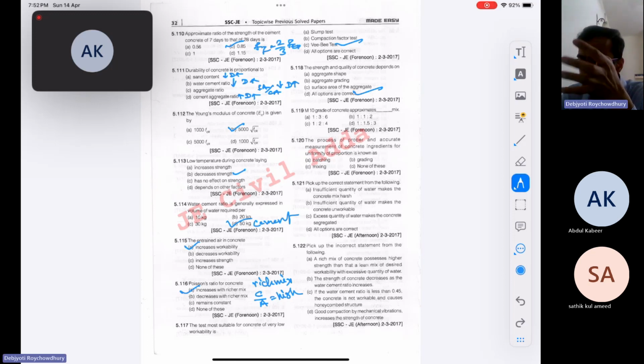The surface area of the aggregate: if the aggregate size is more, the specific surface area is less. If you check the 6 by d formula, if the size is more, the specific surface is less. If the specific surface is less, then the water requirement for hydration is also less, so it will not get the proper heat of hydration. Further, with larger aggregate, cracks will start to propagate along the edges because of the wall effect and other effects. These are the very relevant points.